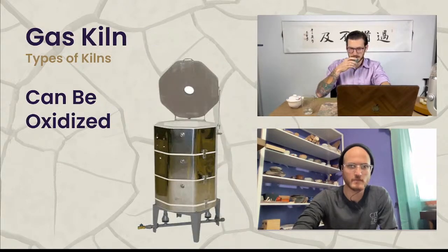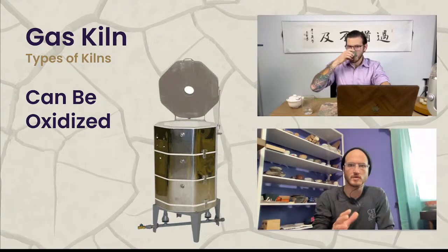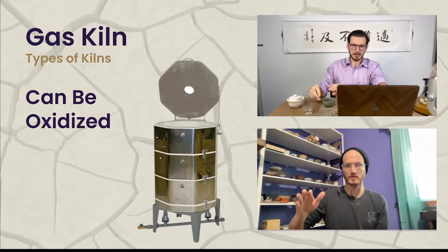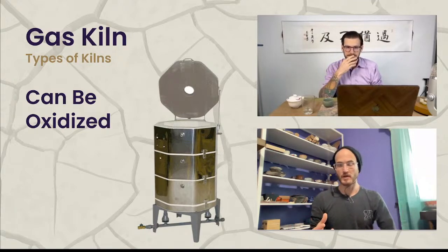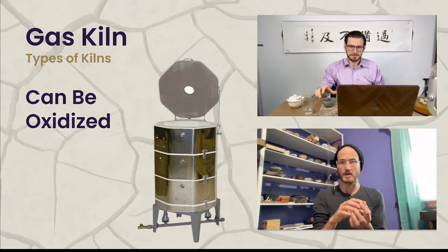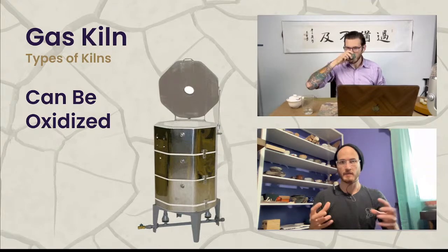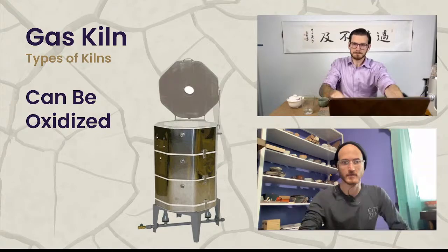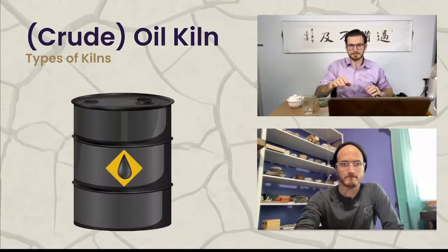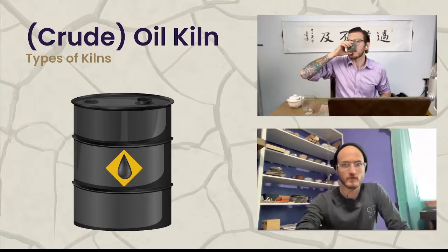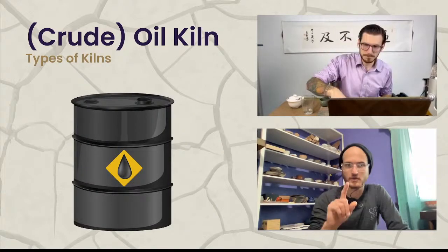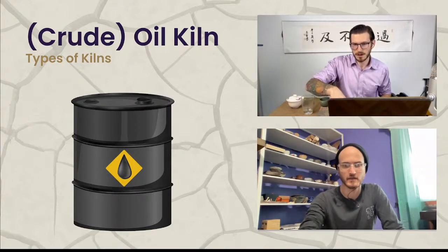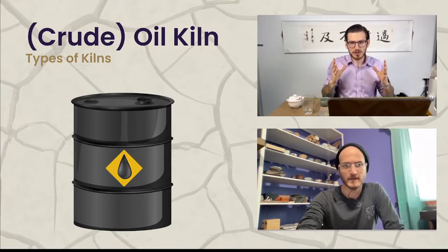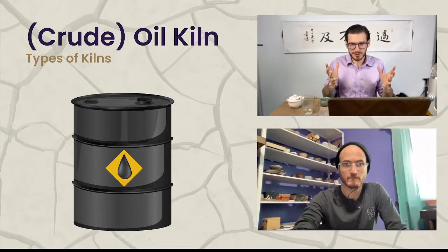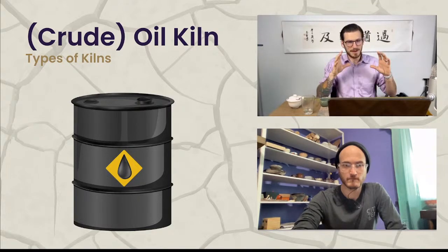Okay, so basically in a gas kiln, you can either have an efficient firing of the flame through the kiln, or you can add more fuel than the kiln can efficiently combust, and that's when you get a sort of smoky atmosphere, and you start to reduce inside of the kiln. Crude oil is another type of kiln where basically you're just shooting oil into the kiln and it's being lit as it flies in. Used commonly.